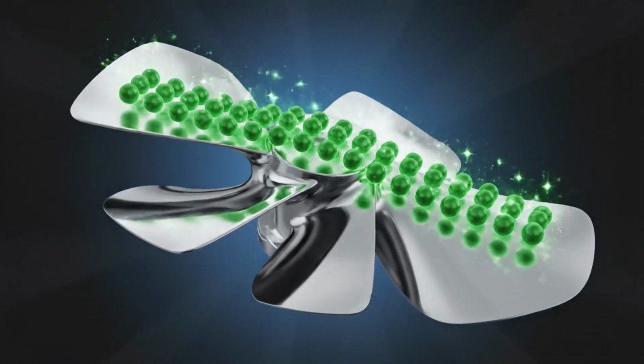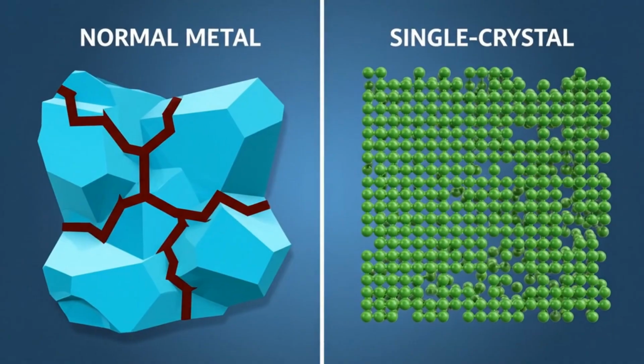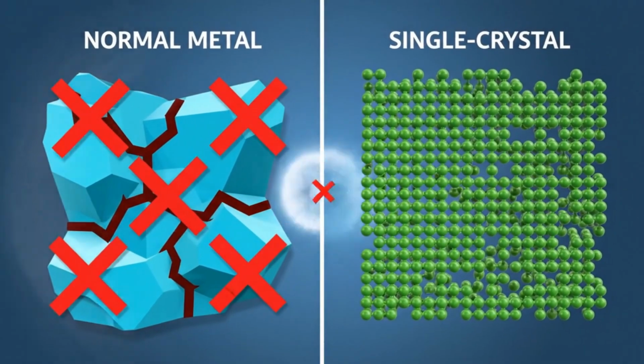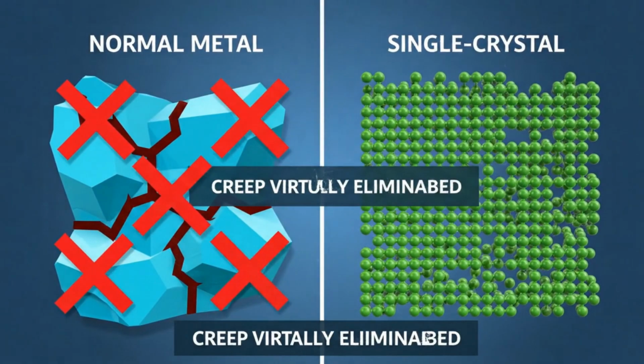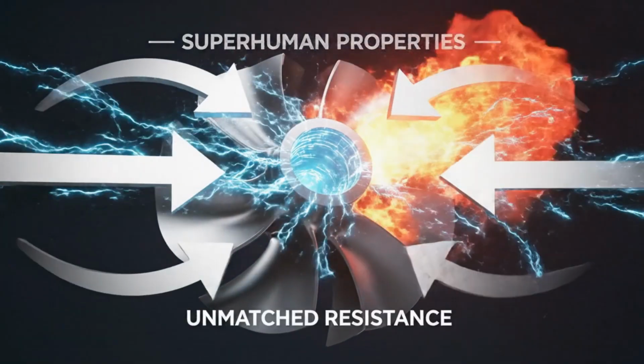From the bottom to the top, there are no grain boundaries. There are no slip planes for the material to slide along. The mechanism of creep is virtually eliminated. This single crystal architecture gives the material superhuman properties. It can withstand temperatures and stresses that would destroy other metals.